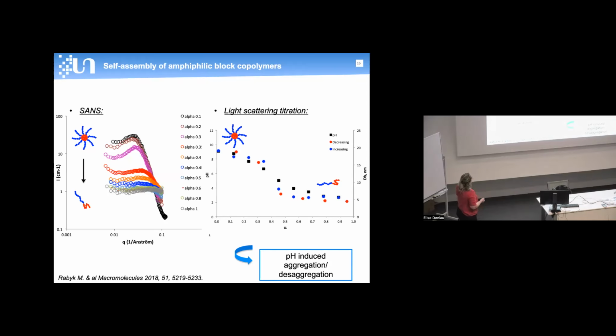So then we study this self-organization under the pH stimuli, also using neutron scattering. And this neutron scattering confirmed the light scattering result with scattering intensity, which decreases when the ionization degree of the monomer units increases. And you can see also that the peak is shifted towards higher Q value, meaning that the size of the aggregate decreased as well.